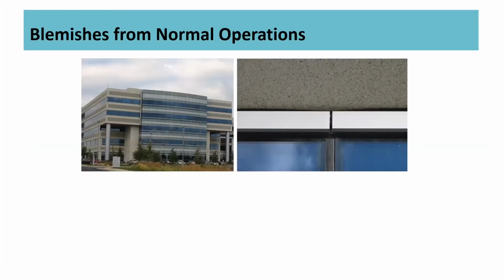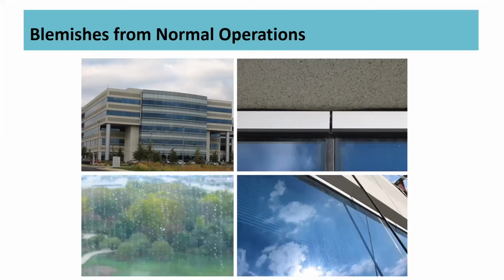Then there's blemishes that occur from what we would term normal operations. In this case, there's unprotected cementitious materials, precast concrete, that's in the same plane as the glass. And what occurs is rainwater runs over the surface of the concrete, leaches alkalis out of the concrete, and deposits them on the glass surface. So they end up looking like water spots, which you think might be pretty easy to remove just by normal window cleaning operations, but they can't. In fact, when we've looked at some of these projects in the laboratory under the microscope, we can see that the alkalis have in fact etched themselves into the glass, creating a small pocket in the glass surface.